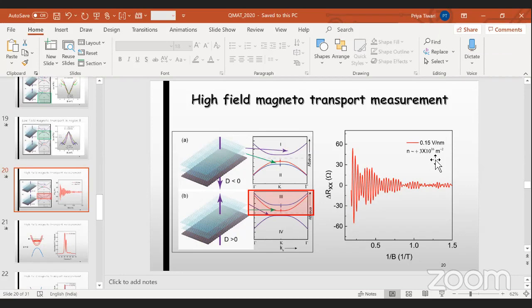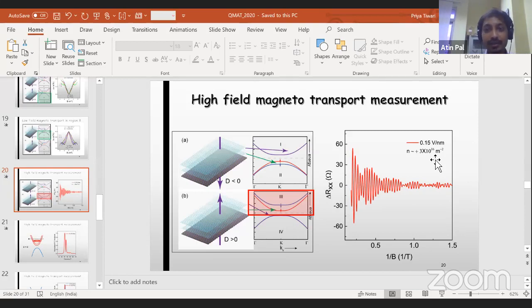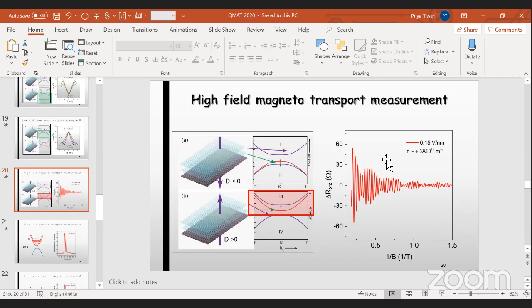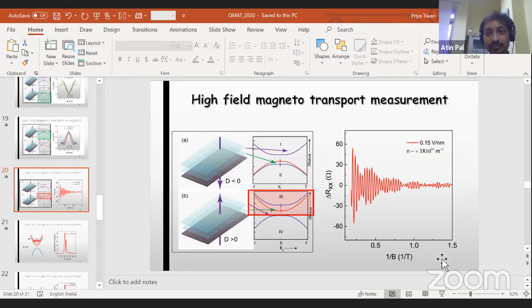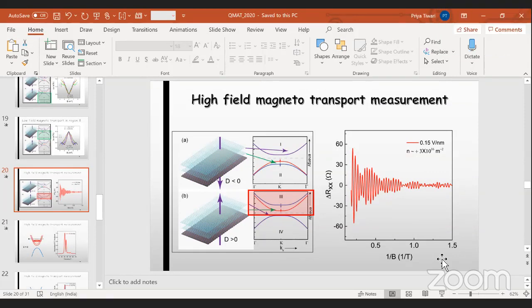Yes, because if it is Rashba, it should increase with the electric field, right? Spin orbit strength. What I want to answer is that depending on the number density, as you go to a higher number density, splitting is becoming more. That's what you expect for Rashba. Yes, and that is what has been seen in another paper also, but they have not done this field dependent measurement. They did it with a single gate, and they also observed this kind of dependence.